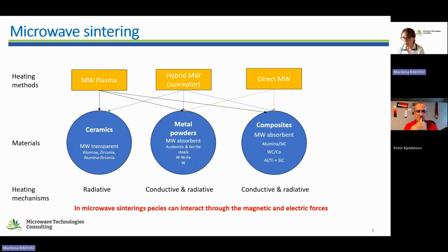I will try to summarize microwave sintering and how we can heat different materials with microwaves. I started with ceramics. Once again, they are microwave transparent, so they don't absorb microwaves as such. As examples, I have here sintering of very dense, transparent alumina, zirconia, and a mix of alumina and zirconia. These are metal oxides, which are transparent to microwaves. Then metal powders: because they are powders, they do absorb microwaves. It's not like a metal wall that you send your microwaves onto. Metal powders absorb microwaves really very well, a little bit too well.